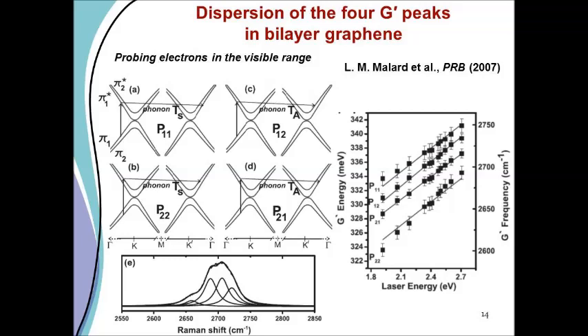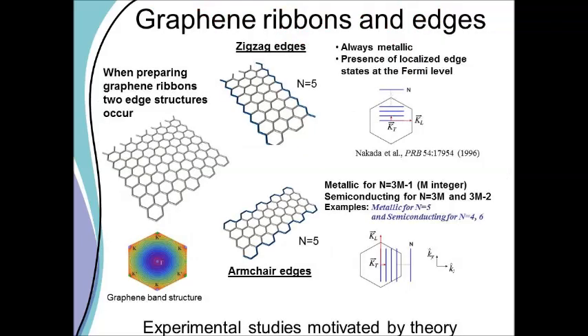And if we do it in second order, we get all these different lines. So we have many things in the spectra to look at and measure. So, high resolution. Another topic where we get big amplification. Here's a ribbon. A ribbon is very tiny. It's less than a nanometer or so across, with 5 different rows of carbon atoms. The carbon-carbon nearest neighbor distance is 1.4 angstroms, so it's a small number. Yet we get a big amplification of signal that you could see at the edge.